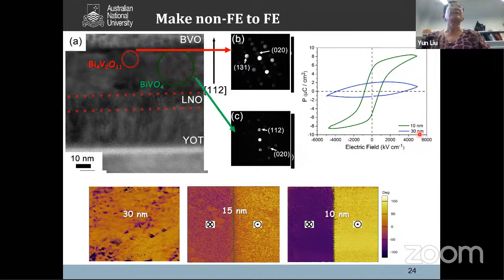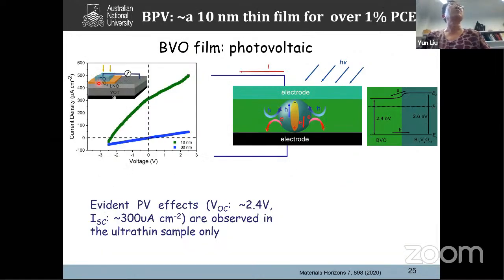And if you look at this ferroelectric polar domain, if you apply different voltage in different directions, you can see the domain contrast from this domain image. But if you increase the thickness, you couldn't see that. Okay, and then we can deposit a transparent ITO thin film electrode on top of this. So with only a 10 nanometer thin film with two electrodes, we actually create a heterojunction in this narrow band gap material.